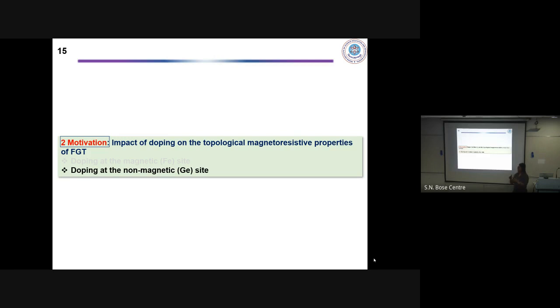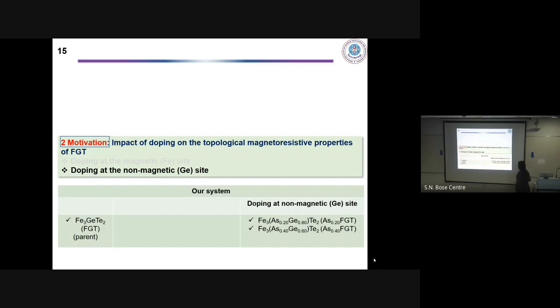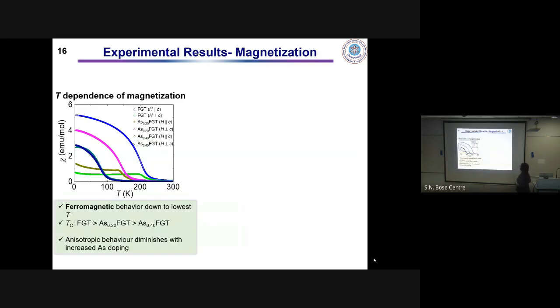So okay, we have doped at the magnetic side, but it is known that in these kinds of systems, the iron concentration plays a key role in governing the magnetic properties. So we thought, if you do not disturb the iron side and instead dope the non-magnetic side, do you even expect to see any changes or not? With this, we started studying the impact of doping at the non-magnetic side, the germanium side, on the topological magnetoresistive properties in this system. These are the two concentrations that we have been successful in growing, and we have studied only these two systems.